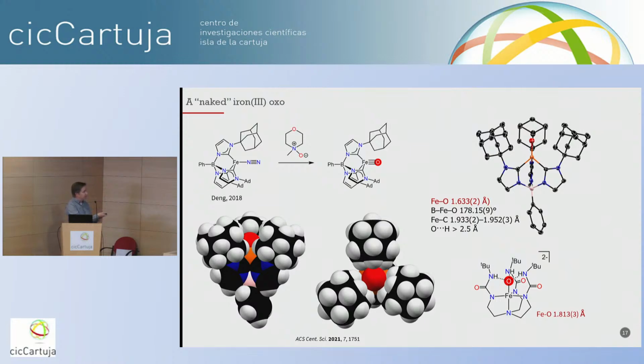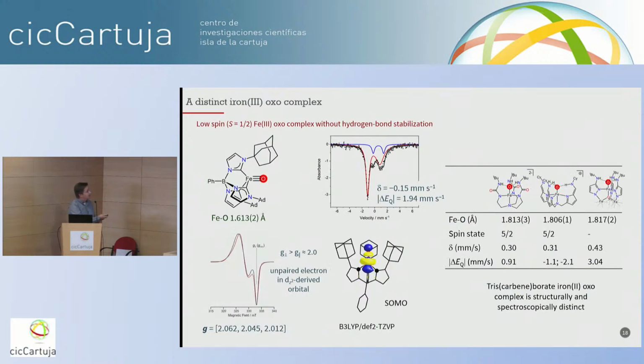If you look at the Mossbauer spectroscopy, this is going to tell us something about the oxidation state and electronic environment. So we see the isomer shift, so that's the midpoint of this doublet here, is at minus 0.15 millimeters per second. That tells us something about the oxidation state, and we can compare with iron imides we've made before that are also iron 4. This is very comparable isomer shift, so it's very consistent with higher oxidation state iron.